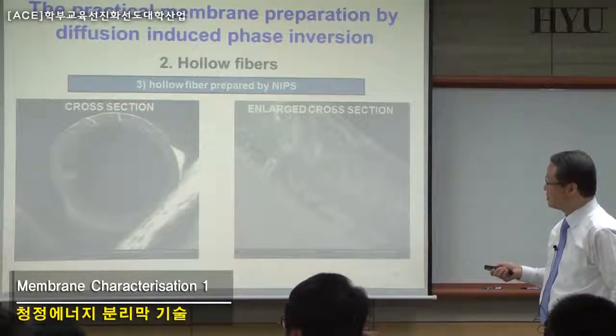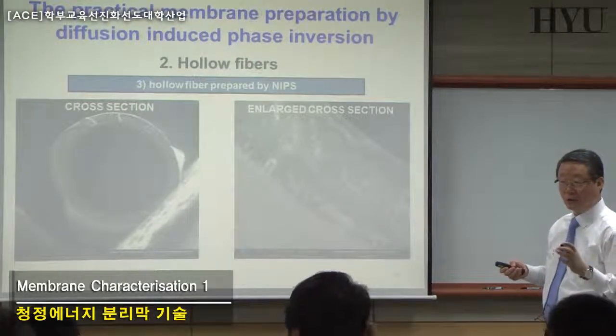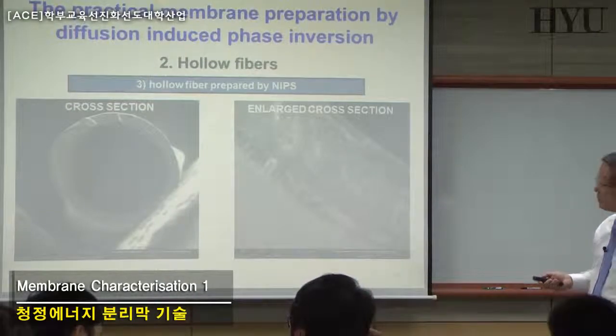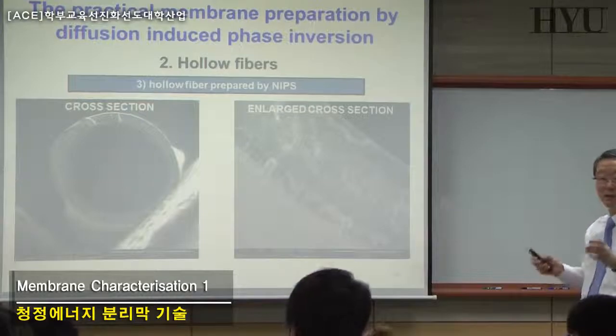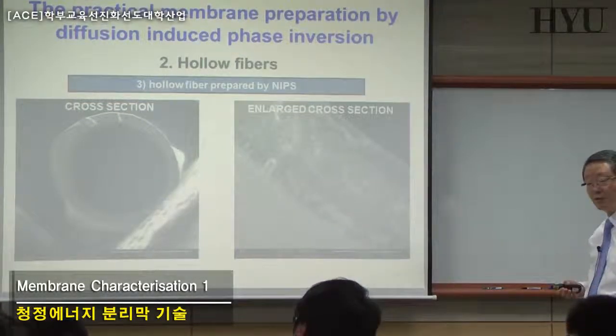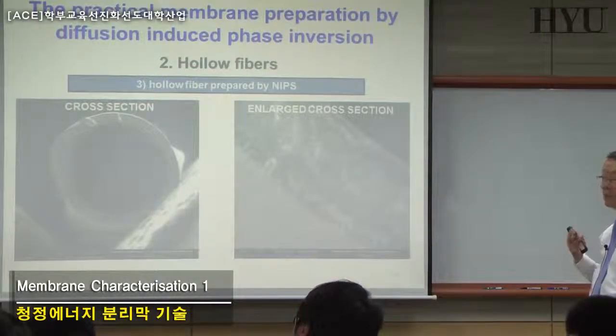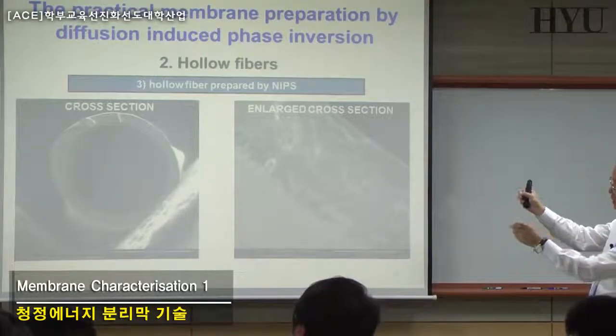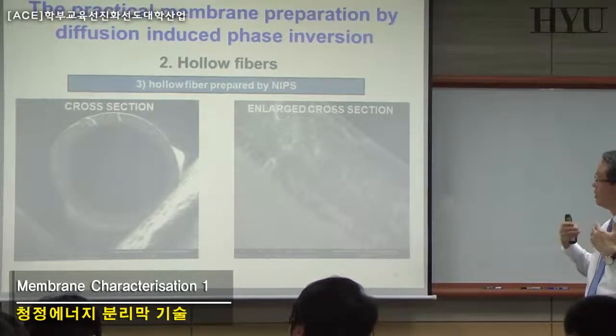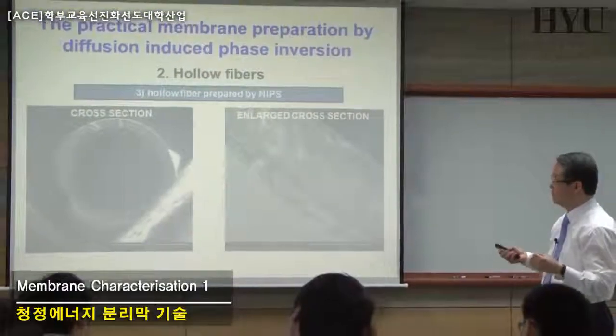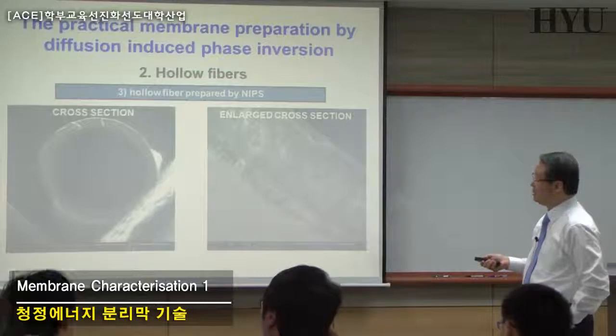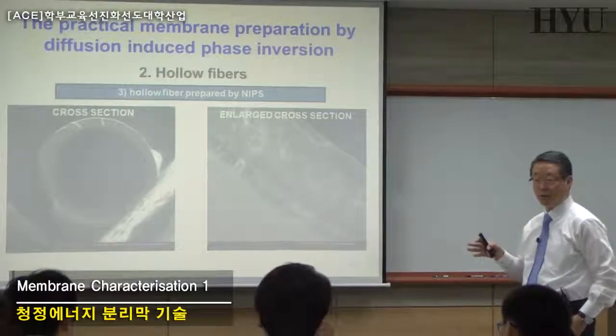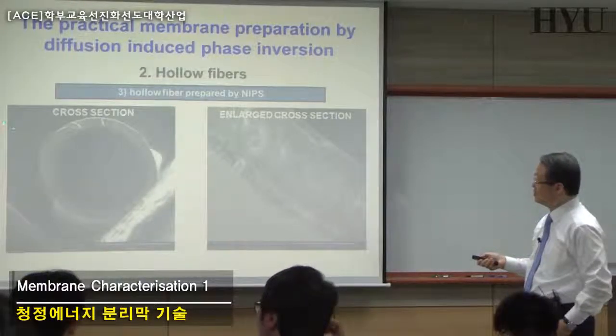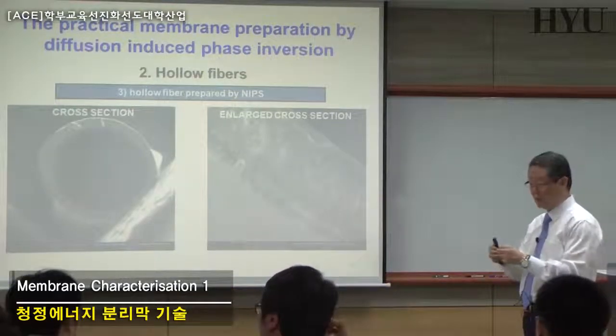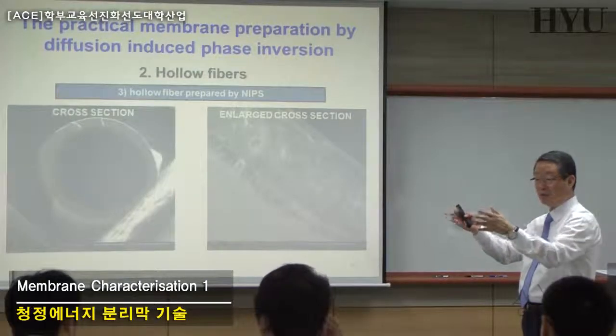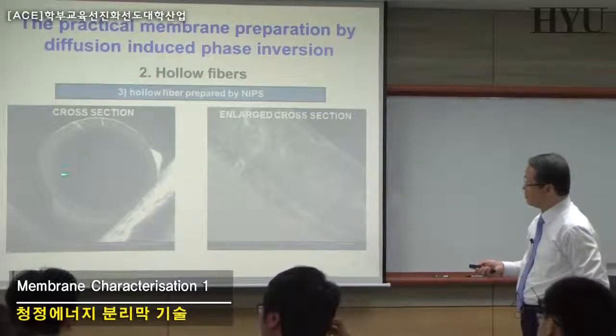The wall layer thickness in this case is very small, maybe less than 10%, and usually for a high pressure gas separation membrane it is about 50%. So 50% of your full outer diameter is filled with the solid structure, and with that 50% wall thickness ratio, you can use that membrane for high pressure gas separation, whereas this thin layer could be used for low pressure, for example microfiltration. The reason why the thicker wall thickness ratio is necessary for high pressure application is that if you apply the pressure from the outside or from the inside, of course high pressure will burst your fiber, so you need resistance to those pressures by increasing your wall thickness ratio.